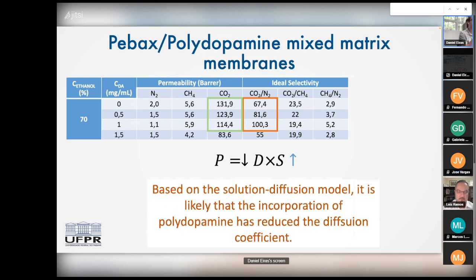To explain that, we could do simple sorption tests, but we don't have that kind of equipment here yet at our lab. So we have to explain that in different ways. If the diffusion coefficient is being reduced, what's probably happening is that polydopamine is interacting somehow with the polymer, reducing the flexibility of the polymer chains, or reducing the fraction of free volume. So those are the two mechanisms that can reduce the diffusion coefficient.